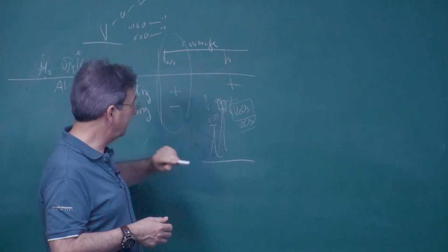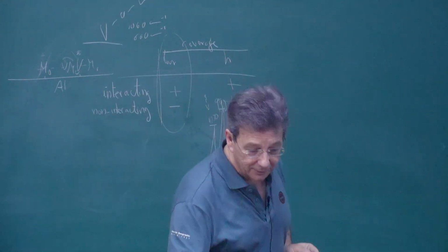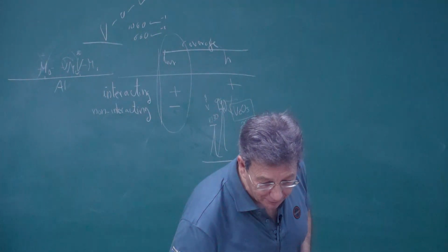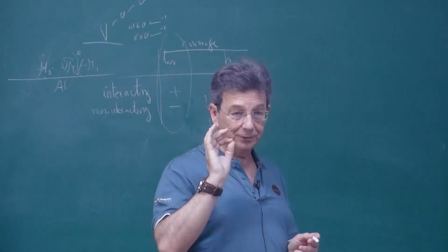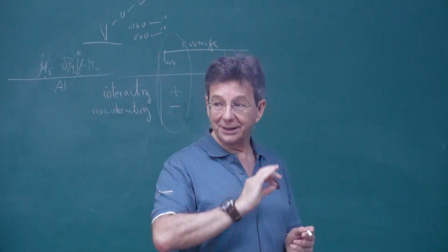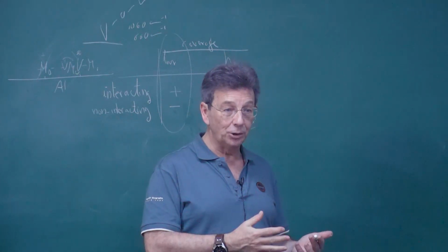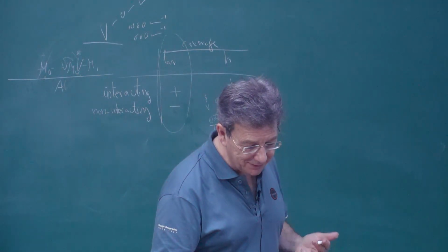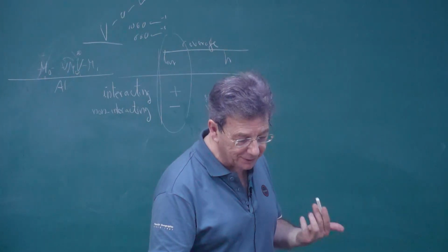So even if you see these sharp bands, like we observe here, like there is a little sharp band already at 990, like this little bump here, or that one there, that means that you are just getting the minimum expression of the vanadium pentoxide crystallite. Raman is reporting that nicely. X-ray will not be able to report it because it's below 3 nanometers, but Raman is very sensitive. So basically this is slightly above the monolayer, and 90% will be dispersed vanadium and a little bit crystalline vanadium.